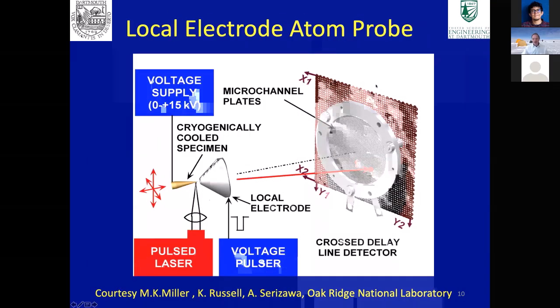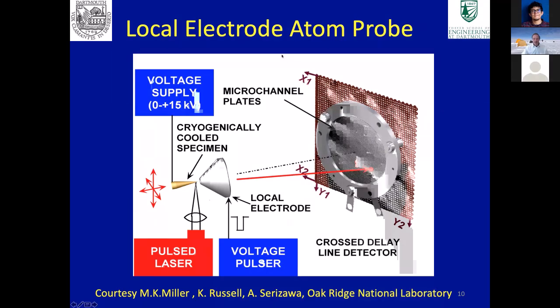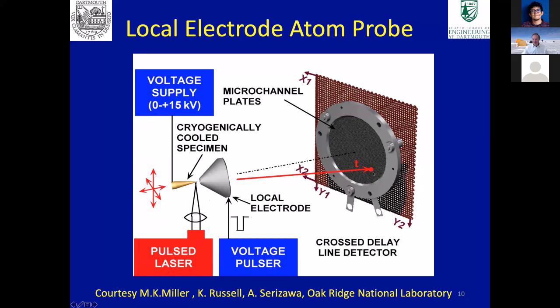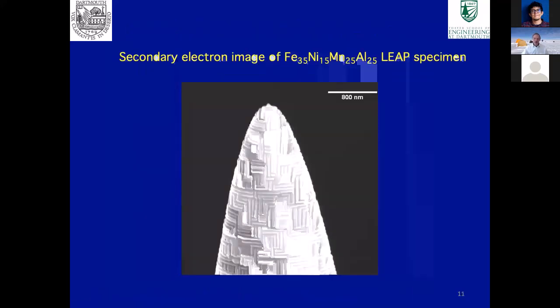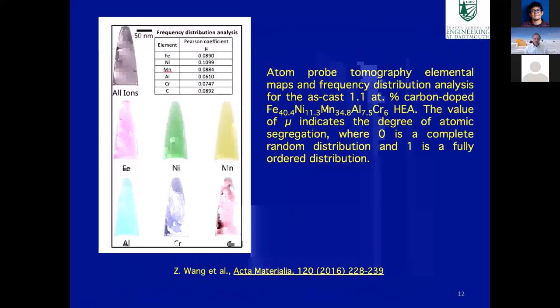We can also look at the arrangement of the atoms in the structure using atom probe tomography. For those of you not familiar with this technique, we use what's called a local electrode atom probe, where we make a thin needle of our material and put that in front of a local electrode with a very high electric field on it. Then we pulse the field, and this strips off atoms from the surface of the needle. These travel through the electrode and impinge on a microchannel plate. From the position they hit on the plate, you can figure out where they came from in the specimen, and the time they took to get there tells you what the element actually was. And this is what one of those needles looks like, one of our alloys.